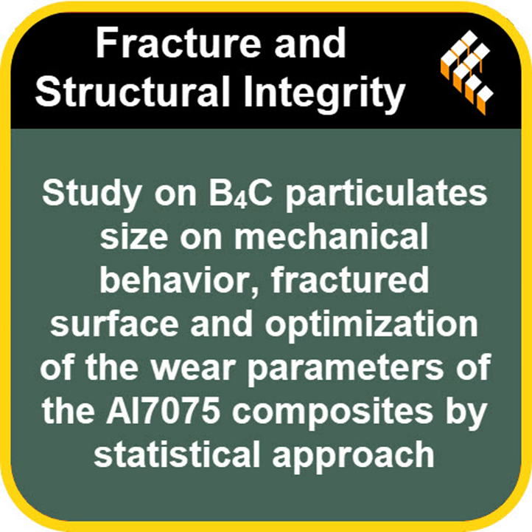Okay. And distance? The COF increased with increasing sliding distance. Ah, the opposite of wear rate. Right. And that's probably because, over longer distances, more wear debris accumulates between the surfaces. While some fills valleys, excess debris can act like grit, increasing the frictional forces. So a really complex interplay of factors.